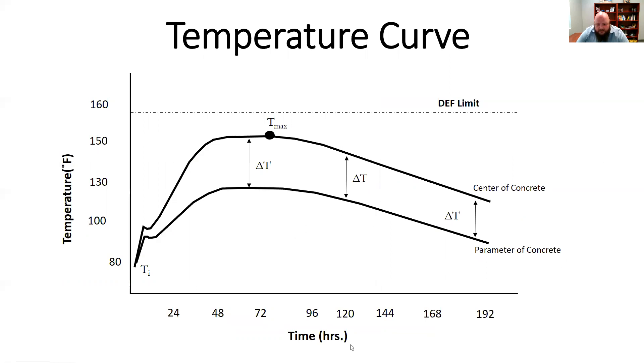We have two different sensors. One sensor is in the middle of the concrete — that's the top line on the graph — which measures the maximum temperature. Then we have another line which is the perimeter, the very edge of the concrete, which should be the coolest. We measure the T-max and then track the differential between these two lines over time to find the biggest difference.